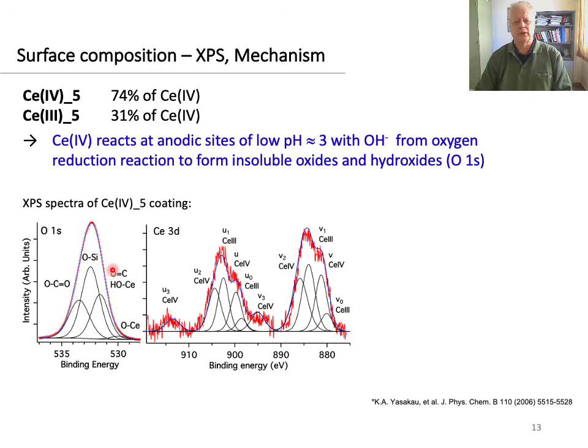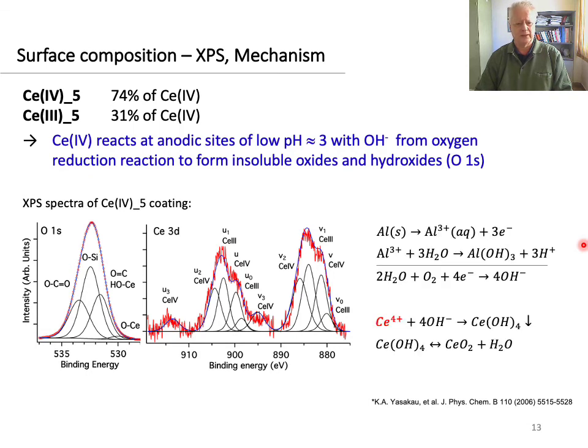By deconvoluting the oxygen 1s and the cerium 3d spectra, the XPS results show that the self-healing ability of cerium-4 containing coatings in pits and artificial defects can be related to the higher quantity of cerium-4 species. In this process, leached cerium-4 ions react at the bottom of the pits, at the low pH of these anodic sites, with the OH- ions produced in the oxygen reduction reaction, leading to the formation of insoluble oxides and hydroxides, preferentially formed at intermetallics that act as sites for cathodic protection.